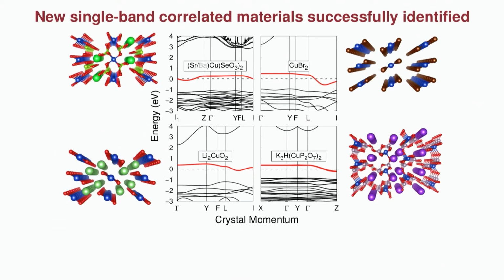So I'm showing you 4 here because 2 of them are essentially the same. If you switch out strontium or barium, this dispersion relation looks basically identical. You can see that in each of these cases, we have in red this isolated band that's half filled and half unoccupied. You can see that there's appreciable energy separation between the bands above and below.